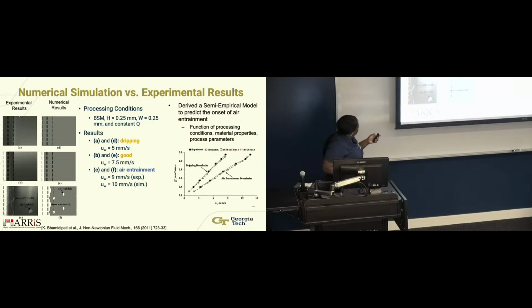So if we compare the experimental results to the numerical results, what we found is that under certain conditions, for A, we found dripping. This is the center between those two plates, the fluid coming out, and you can see it comes out and goes backwards instead of being pulled forward.